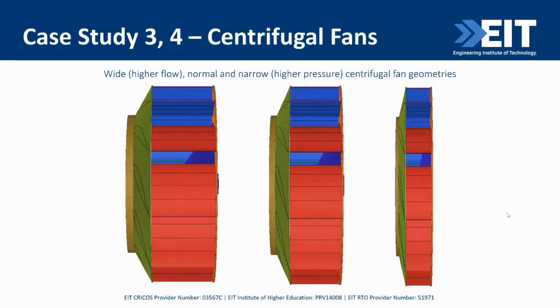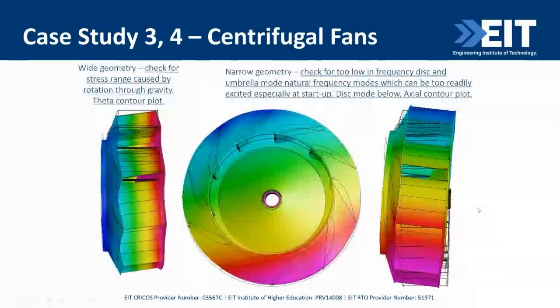Obviously your RPM loading, your centrifugal loading, is the strength load case. The fatigue load case is caused by rotation through gravity, as well as pressure and flow buffeting. But you must calculate that rotation through gravity fatigue load case. And too narrow, you've got to be careful about disk modes getting excited during startup. So we've had both.